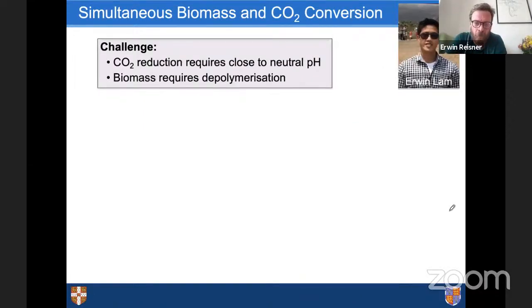Okay, and the last example I want to show on biomass, which just came out online, is work by Erwin Lam that I'm really happy about. It really shows that we can simultaneously convert two waste streams, biomass on the oxidative side and CO2 reduction on the reductive side. And it's also incredible because Erwin Lam joined my laboratory in March 2020, which arguably was not a great time to start a postdoc. Given that the lab was shut 50% for a year, it's incredible that he got all of this done already. The challenge he took on is that to reduce CO2, we really require neutral pH. If you operate under highly alkaline conditions, you trap all the CO2 as carbonate.